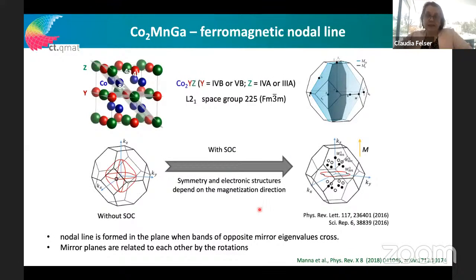In cobalt 2 manganese gallium, as one example of the Heuslers, we have many mirror planes, a cubic symmetry, and an FCC lattice, if you see it from the perspective of only one color. Since it's cubic, if we try to draw the overlap between the conduction and the valence band, because of the cubic symmetry we have nodal lines in X, Y, Z direction, and this leads to this feature, which are the nodal lines in this compound. If we now apply a magnetic field, with spin orbit coupling, we can turn some of the nodal lines into Weyl points, which you can see here.